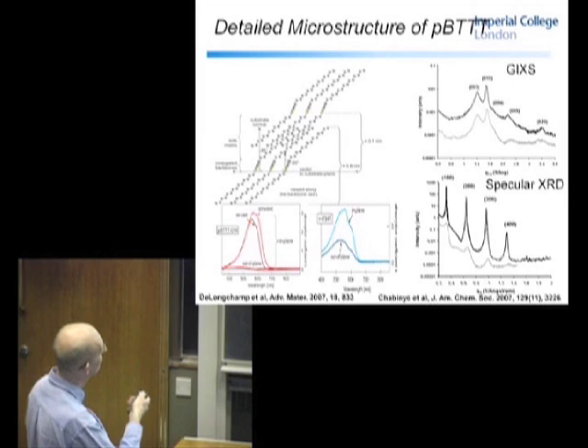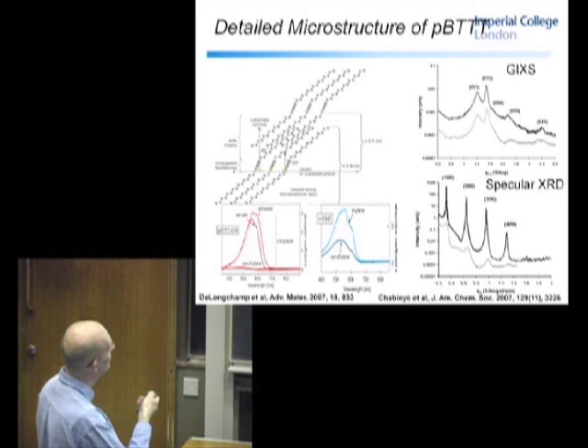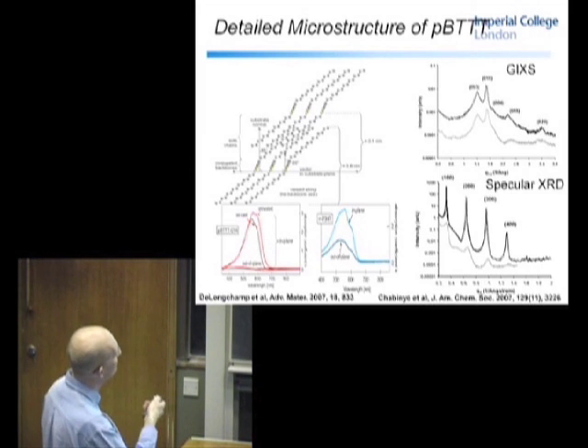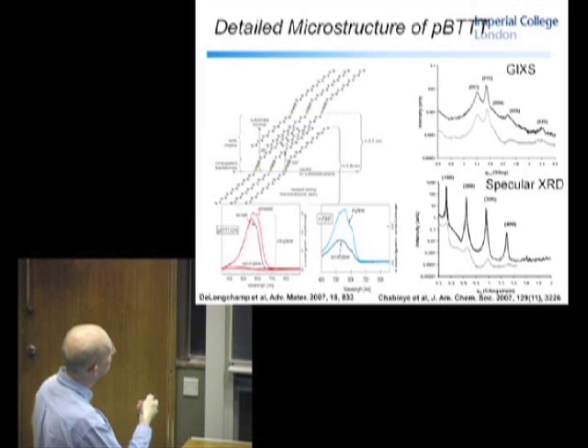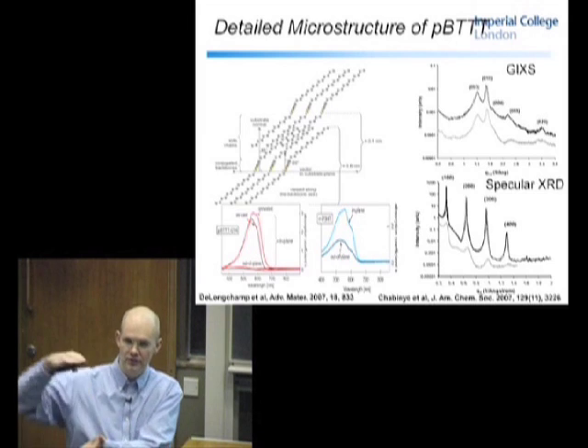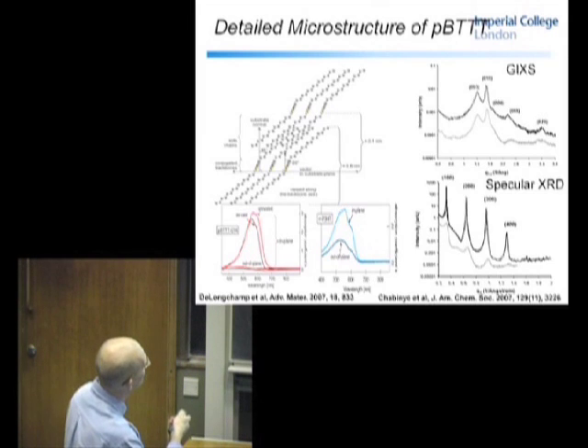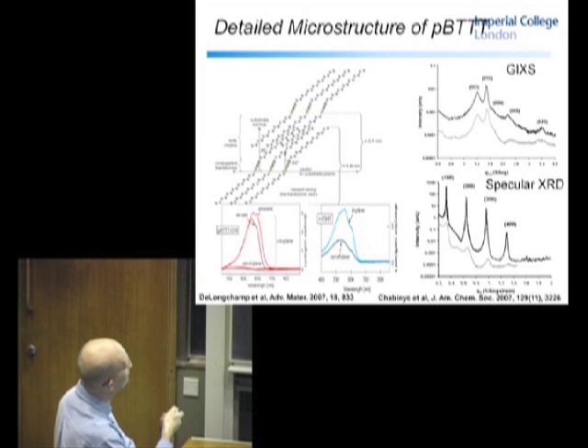way that this packs together, this is a side view of the backbone. It's almost perfectly planar. The alkyl chains project at an angle, but quite interestingly you form these lamella where the backbones pack, and this is the pi-pi distance. But even though the plane of the lamella is in the substrate plane, so if you imagine this is a substrate along this line here, these lamella pack in the plane of the substrate, even though there is a tilt angle of the backbone. But when the second, so this is one lamella, and this is a lamella above, the alkyl chains from one lamella to the next interdigitate, and this gives rise to this highly ordered structure.